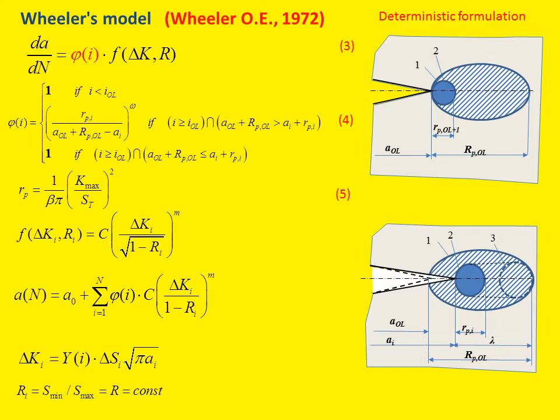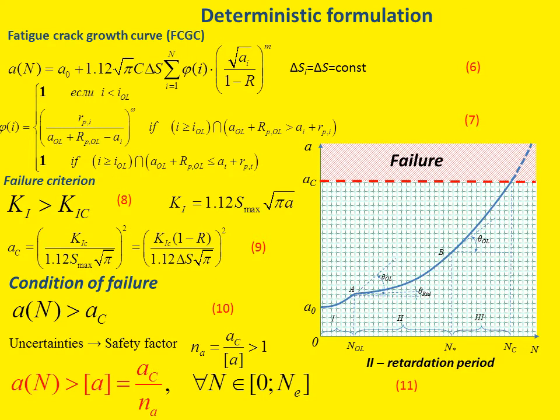Equation 3 can be integrated numerically in finite differences. And by integration of the equation 3, we can get a dependence of the crack depth A against the number of cycles n, or the so-called crack growth curve. Then a critical crack depth is determined using the criterion of brittle fracture, and the condition of the component failure is expressed by equation 10. In view of uncertainties, we can introduce a safety factor and rewrite the condition of failure in the form 11. So this is the solution of the problem in a deterministic formulation.